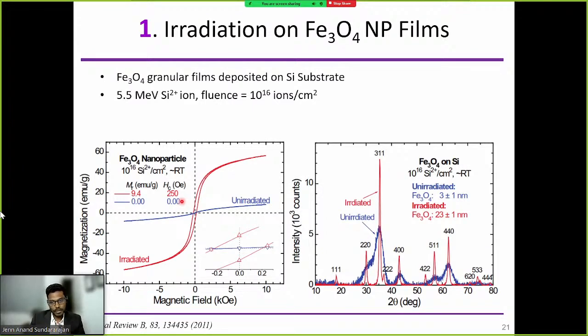And we will take a look at the XRD spectrum here. What we found is the grains have grown huge. You can see the unirradiated films are only 3 nanometers in size, but after the radiation, the grains have exploded, pretty much 7 or 8 times more. You can see it's like 23 nanometers here. And we can see from the thin peaks here that the grain size has grown drastically. So there is a huge change happening here with the radiation.